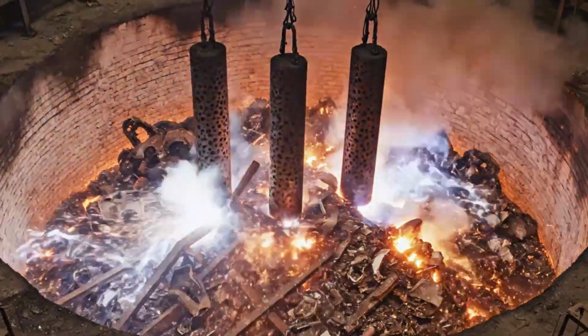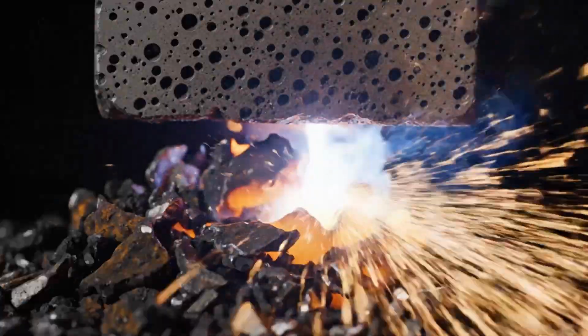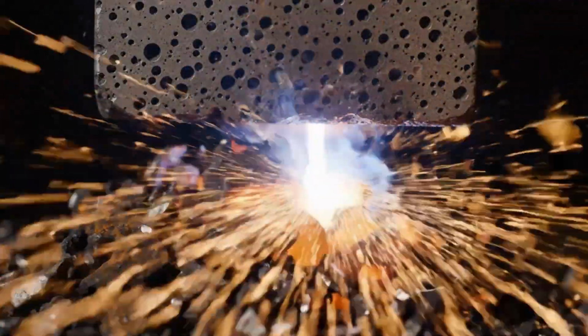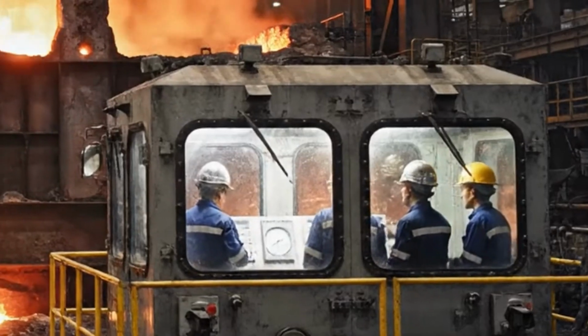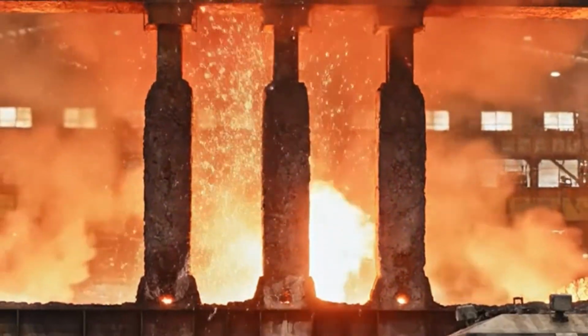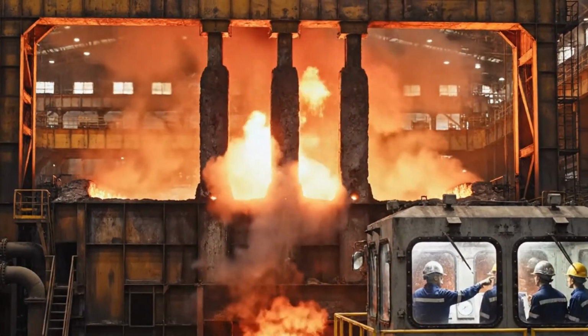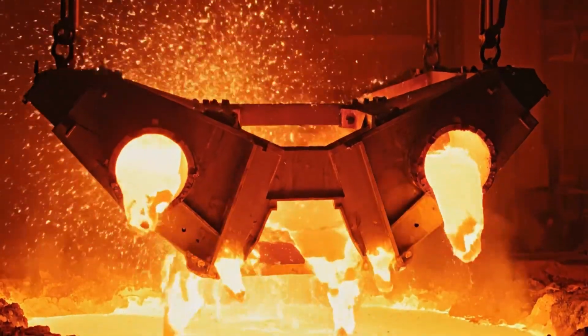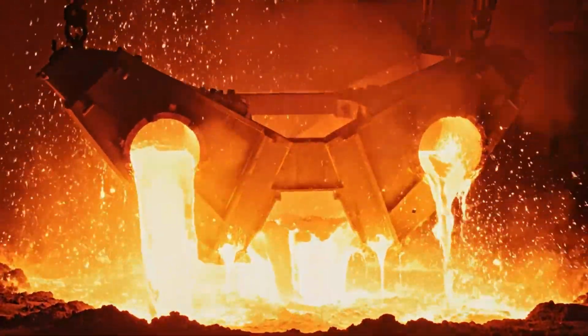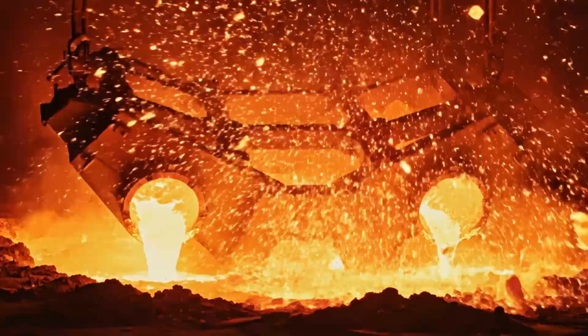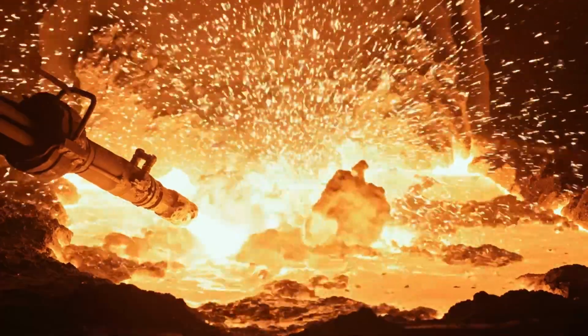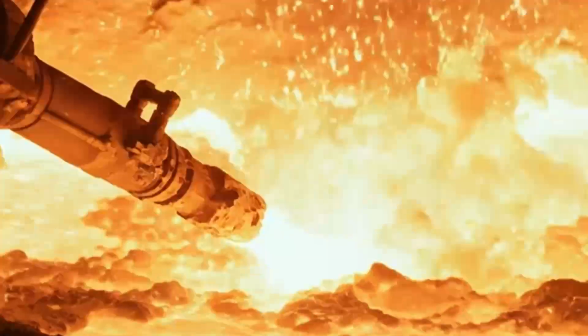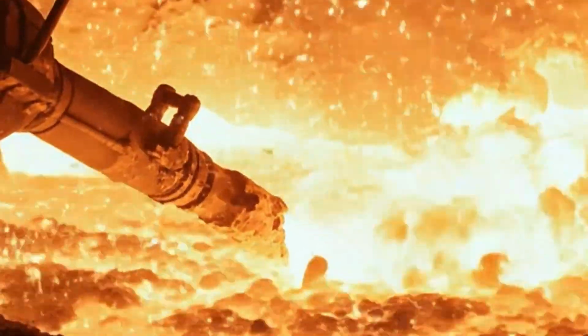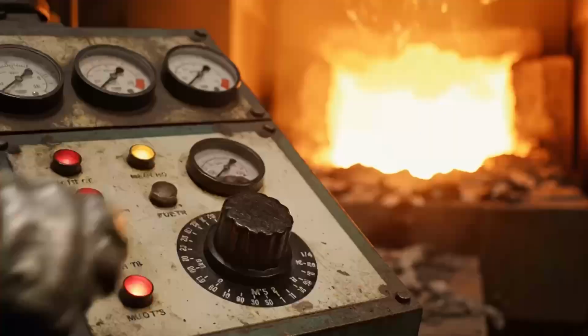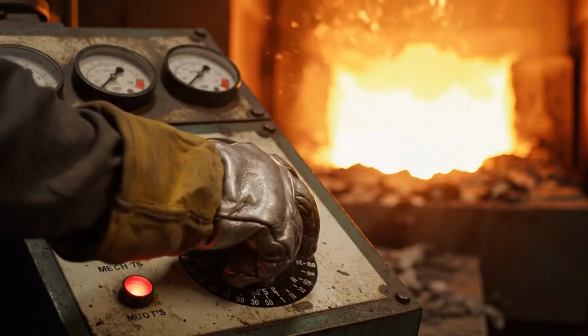During this stage, oxygen is also injected to promote the combustion of impurities and regulate the temperature. At the same time, fluxes, such as lime, are added to form a slag layer on the surface. This slag performs a crucial function. It traps oxides, sulfur, and other unwanted substances, helping to purify the metal. But melting isn't enough. The metal must also be refined. Metallurgical engineers analyze the composition and add elements to correct the carbon content or modify specific properties of the steel or cast iron intended for the part.